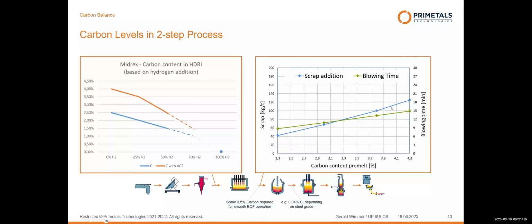The less carbon we have, the less carbon we combust and the less energy we produce in the BOF converter. So that's, of course, less cooling material we can charge to the furnace, meaning the scrap rate that we charge to the furnace is reduced. And that's why, for sure, if we change to a synthetic hot metal from the smelter, the scrap rate on the BOF converter needs to be adjusted.